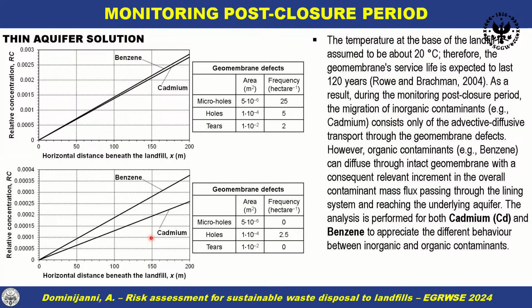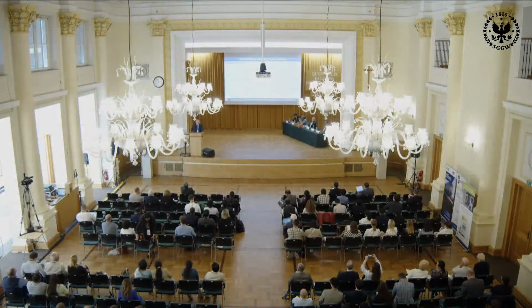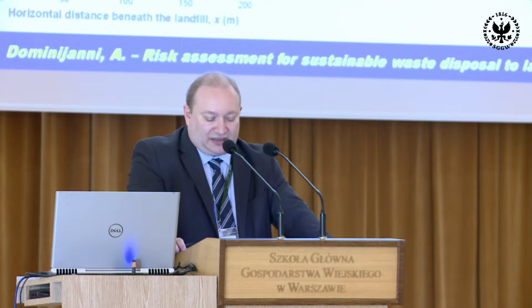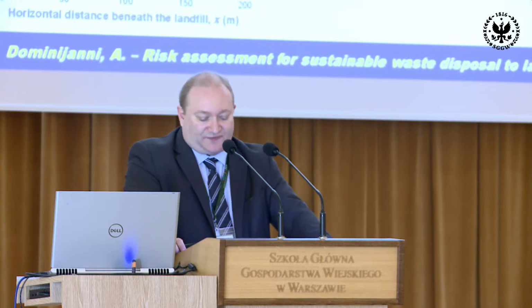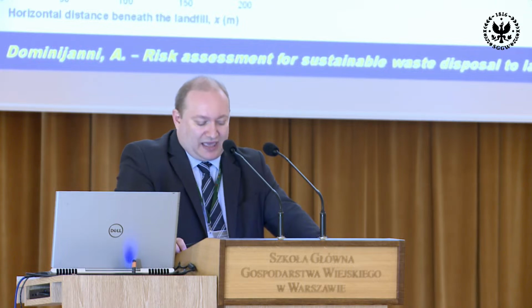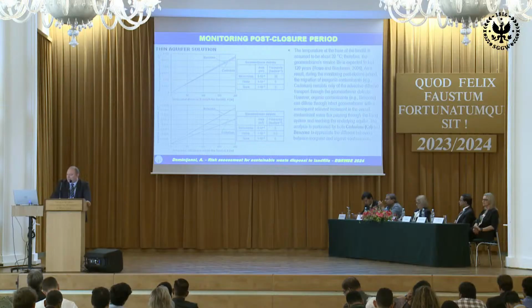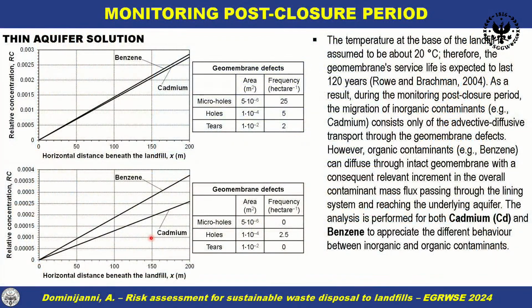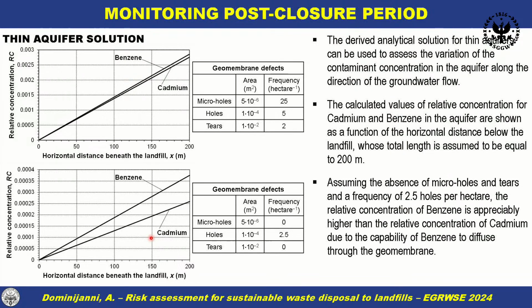Brachman. As a result, during the monitoring post-closure period, the migration of inorganic contaminants consists only of the advective diffusive transport through the geomembrane defects. However, organic contaminants can diffuse through the intact geomembrane with a consequent relevant increment in the overall contaminant mass flux passing through the lining system and reaching the underlying aquifer. The proposed analysis is performed for both cadmium and benzene to appreciate the different behavior of inorganic and organic compounds.